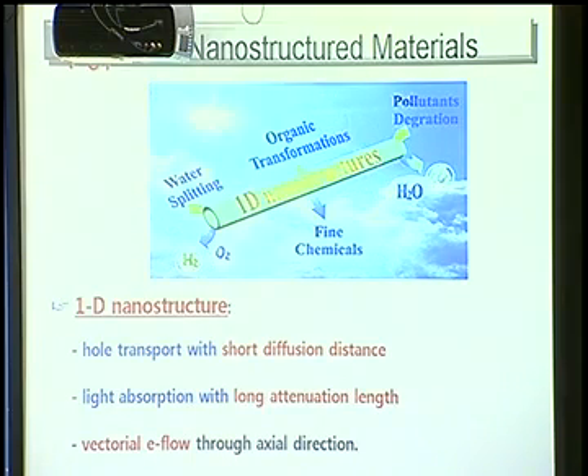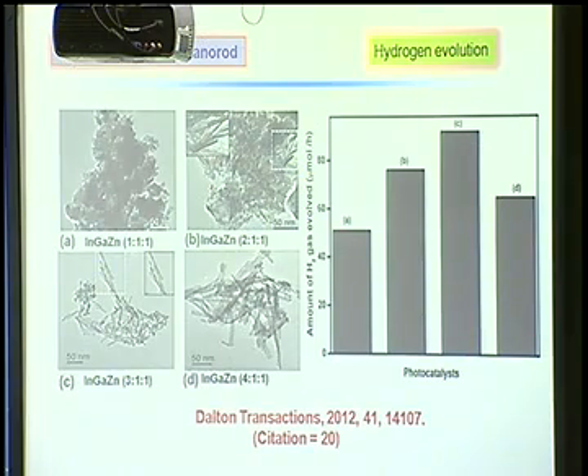And then, how to improve the charge transfer efficiency. By designing a 1D or low-dimensional material, we can improve the charge transfer efficiency, because in a 1D material there is hole transport with a short diffusion distance, light absorption with a long attenuation length, and vectorial electron flow through the axial direction. In this regard, I have developed this material, and it was published in Dalton Transactions in the year 2012.